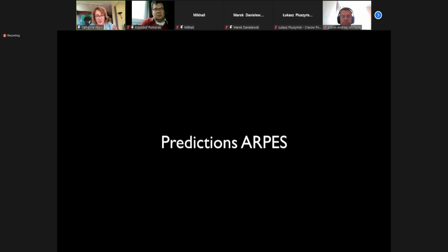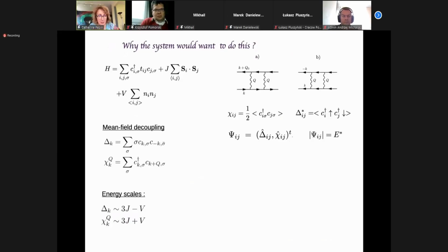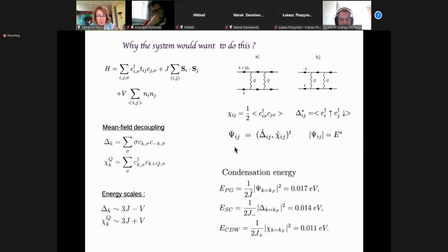So within this theory, we got a lot of predictions. I will go very quickly since I still have a few minutes, I think. We took a very simple toy model. So this is maybe the weakness. We got no microscopic model, but in the toy model, we could put by hand the J and V. We put next nearest neighbor interaction, Coulomb interaction for electrons, so that the charge is a little bit winning over superconductivity. And we decoupled and put the strong coupling by Gutzwiller technique and compared the formation and condensation energy of the pseudo gap, namely, remember it was a constraint, and each of the orders separately.